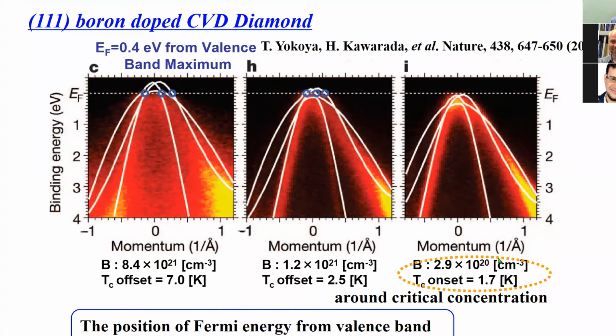Sorry, this is a superconductor sample, 3 times 10 to the 20th, where the Fermi level almost reaches the top of the valence band. This is one of the highest concentrations at that time, 8 times 10 to the 21st, almost 1 times 10 to the 22nd. Then you get the plateau region, and the Fermi level enters into the valence band. So this is one piece of evidence explaining why superconductivity takes place.